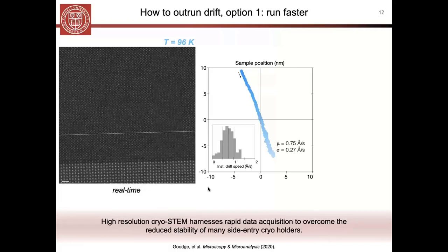We can actually quantify the amount of this drift by tracking the sample position over a long time. In this case, it's just over 4 minutes. You can first of all see the very directional nature of this drift. Again, that's the direction of the rod and the direction of thermal drift in this particular acquisition. We can extract a mean instantaneous velocity here, which is about 3/4 of an angstrom per second. That's the kind of drift speed that we're up against under a lot of these in situ cryogenic conditions.